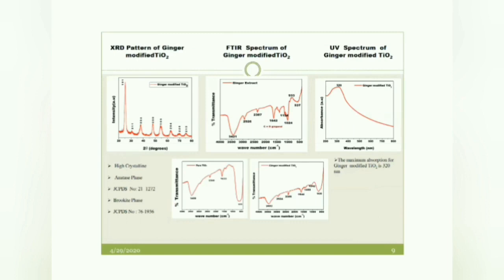But in the FTIR spectra, you can see there is a band around 1642, which is from the ginger extract alone. So I can see the C=O from the gingerol, which shows the presence of ginger. The UV spectrum of the ginger modified sample gives around 320 nanometer, where the maximum absorbance has increased when compared with the pure titanium dioxide nanoparticles. When it is modified, you can again see in the FTIR spectra around 1644, which shows that gingerol is present even after I modify it with the titanium dioxide nanoparticles. So this comes under the FTIR analysis.